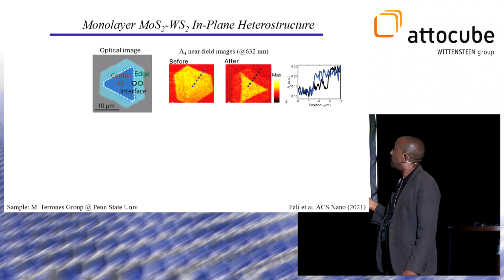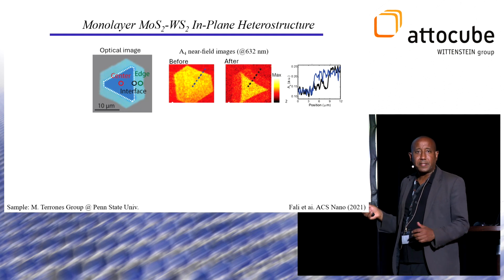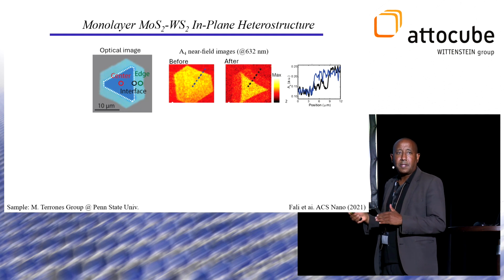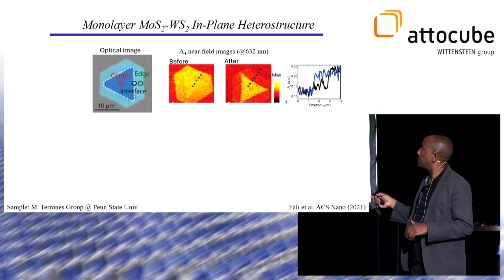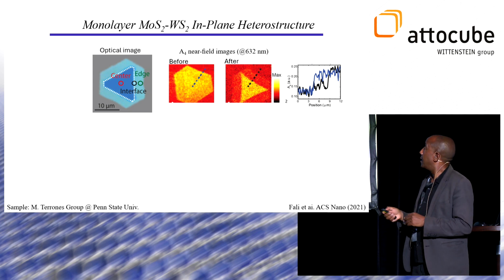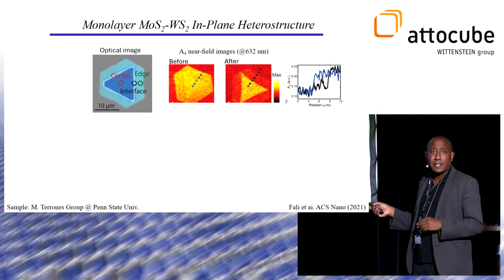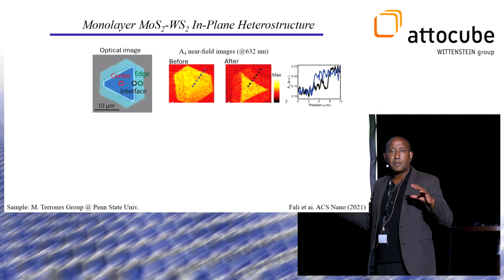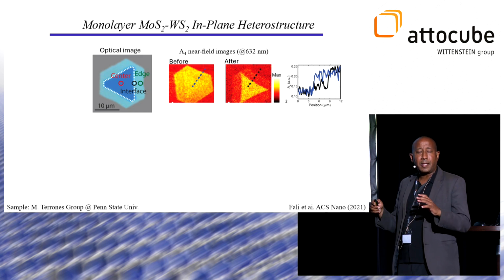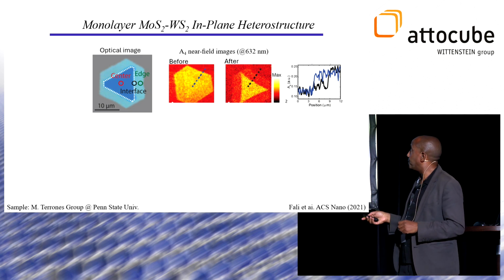And we explain this phenomenon by the interface. The alloyed interface protects against oxidation because it's a thermodynamically stable interface that protects the inner layer from degradation.